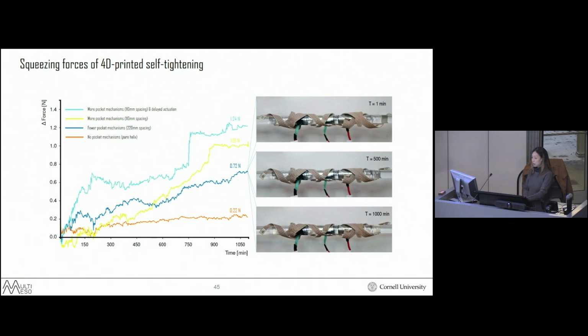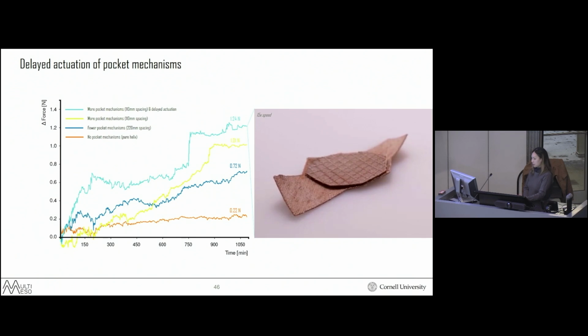So we measured the squeezing forces of our 4D printed material system and compared the different combinations of the two mechanisms. So you can see the helix mechanism without any pockets in orange, which generated fairly low forces. Then the addition of those pocket mechanisms in low and high densities was able to generate increased forces to varying degrees. But what was the most effective strategy we found was that by programming a delay in the pocket mechanisms, that was the most effective strategy for increasing the squeezing force.